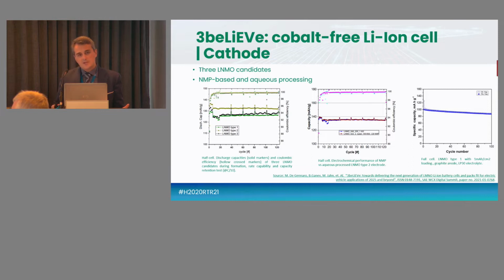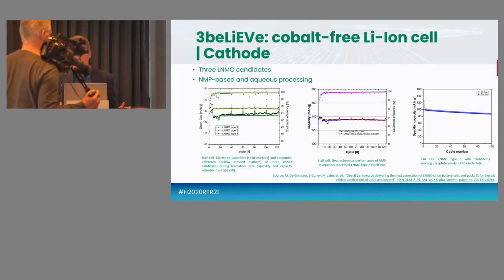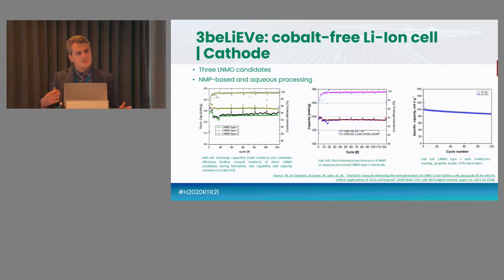And on the right-hand side of the slide, you can see the first results on the full cell. These are not the final cell of 3 Believe. 3 Believe will deliver the final chemistry at the end of April, so approximately 1 month's time, but these were some results which are at the moment some months old, where we see that coupling the type 1 LNMO with an LP30 electrolyte and the graphite anode, we have a drop in capacities as was expected. And now we are working on inserting silicon in the anode to increase the capacity. We are working on 5%, 10%, and 15% of silicon insertion in the anode. Yes, that's the snapshot on chemistry.